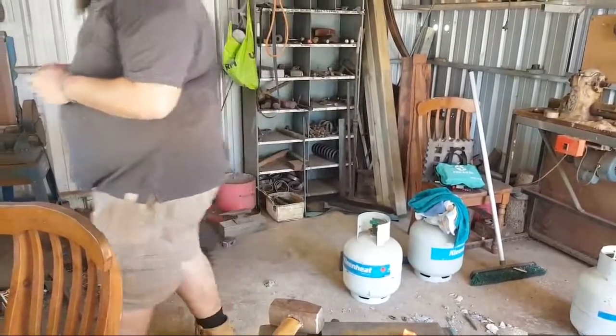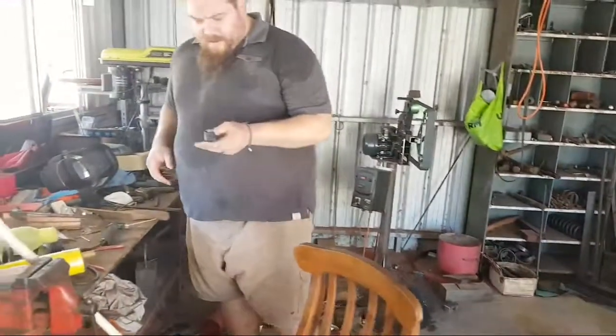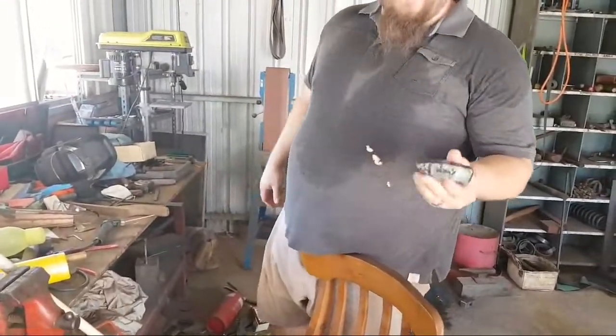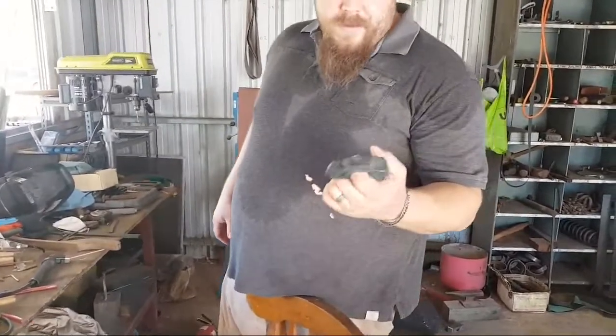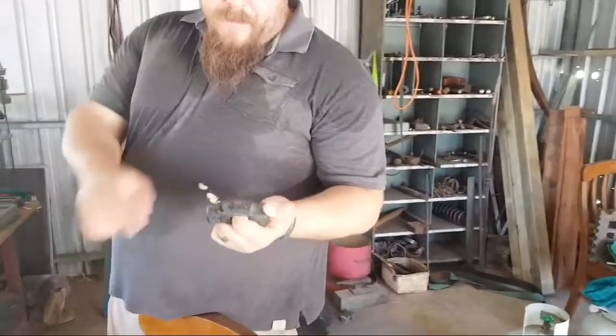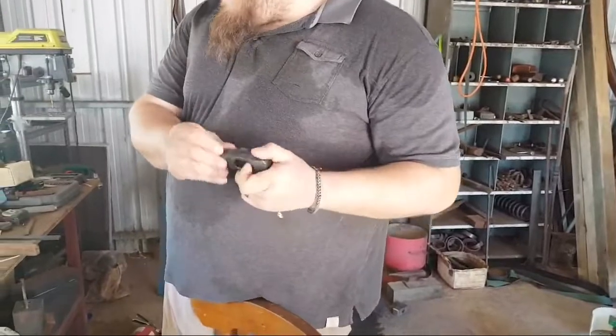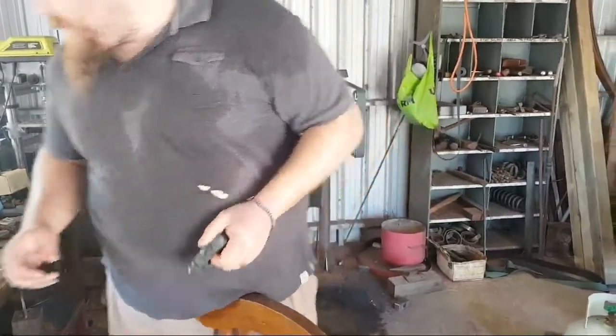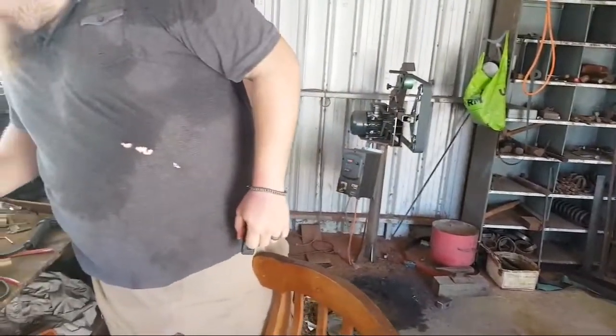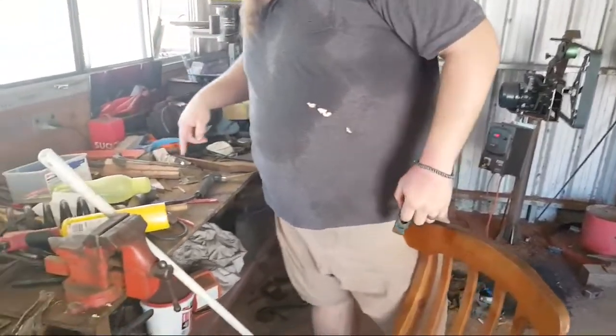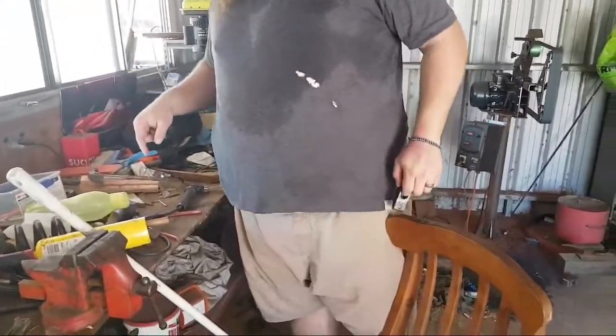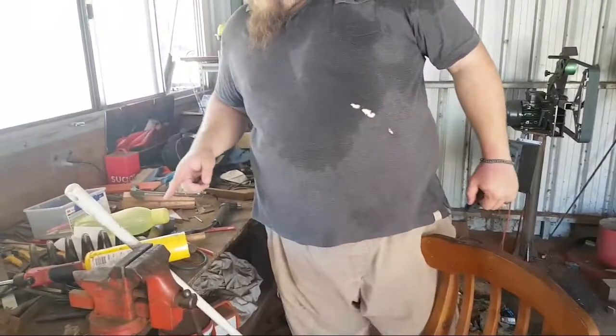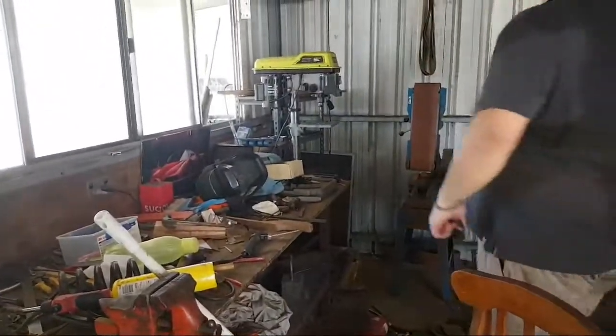Alright, so that happened. I can see by the grey colour that it's turned that martensite has formed. Yeah. The grey behind the black. The black is just the iron oxide, the grey is the raw material. Now, one thing about 1045 is even if you harden it fully in water, it will not be hard enough to skate a file, which I'm looking for a file right now, but...